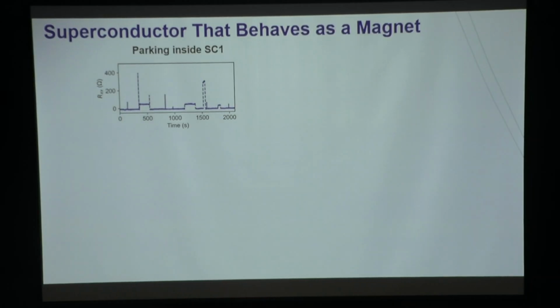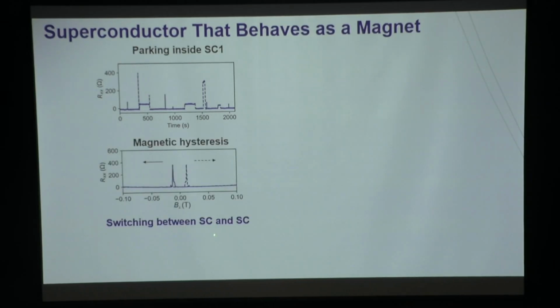leads. Okay? And the next thing we did is staying at the same state and test its response to magnetic field out of plane. And what we found is that you can actually observe some hysteresis. What do I mean by hysteresis in a zero resistance state? Isn't it always zero resistance? Well, what you actually see is that there are two spikes as you scan magnetic field that deviate from zero, and they don't overlap. You scan forward and backward. There is a clear separation between the two non-superconducting states, and that tells you this is like a magnet.